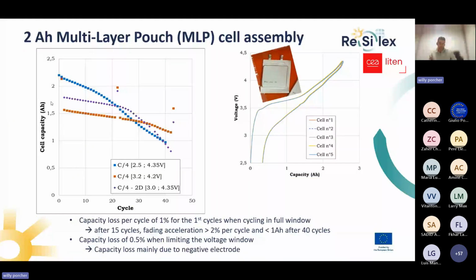Now on the capacity retention, which was not solved previously at cell levels: when we have the full window, the full capacity cycle of the cells, we have a 1% capacity loss, as expected from all cells measurements, shifting even to 2% of capacity loss after 15 cycles, and no more than 1 ampere hour after 40 cycles. So really low capacity. Even if we decrease the voltage window or the capacity use of the cells, we can improve to 0.5% capacity loss per cycle, but really it's not good enough.